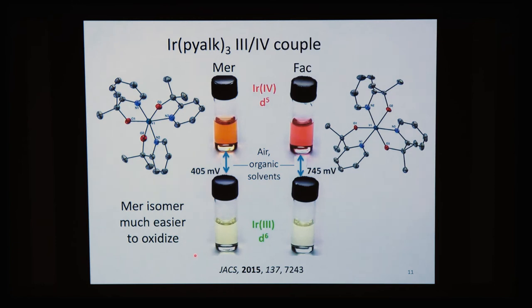Now, if we move to iridium, that's the heavier element immediately under rhodium, so it's easier to oxidize. And so in the meridional case, a mere 405 millivolts, which is quite a reasonable amount of potential to apply. And indeed, all of these compounds are air oxidizable. So if you leave them in the air, they go from the yellow iridium 3 form to the iridium 4, which has these nice colors.